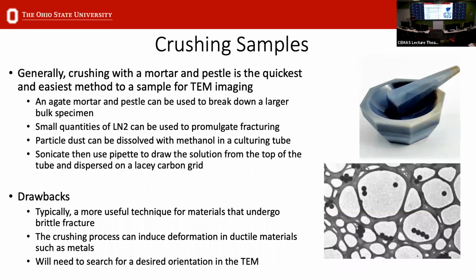And I'll just briefly mention that a technique that is available is to just crush your samples. And this is probably the easiest way of making your sample. It's not applicable to everything, but you would basically use a mortar and pestle. This one is an agate mortar and pestle. You would just basically crush your sample down. You could also add liquid nitrogen into the mortar and pestle to promote fracturing of your sample.